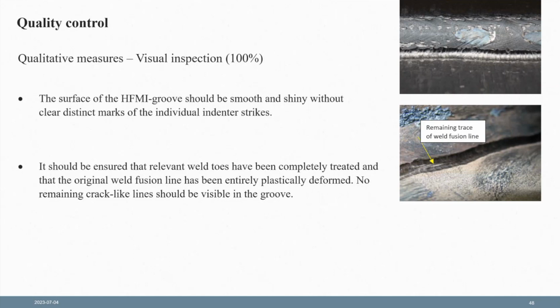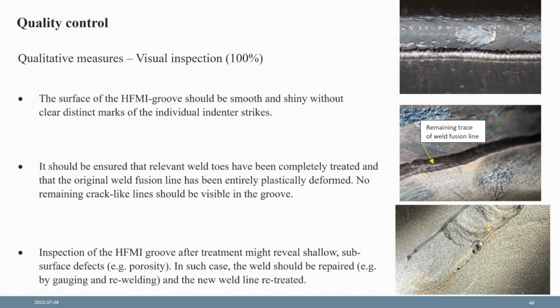If there are undercuts in the size of 0.2 or 0.3 millimeters in the weld, then HFMI treatment will not be able to remove them totally, and there will be traces remaining there. And in this case, this area needs to be ground, for example, and then treated again. And in some cases, we've seen in practice that HFMI treatment reveals shallow local defects in terms of cold cracks or porosity that were revealed after the HFMI treatment. And this, of course, needs to be gouged out, re-welded, and then retreated again. It cannot be allowed in this case.